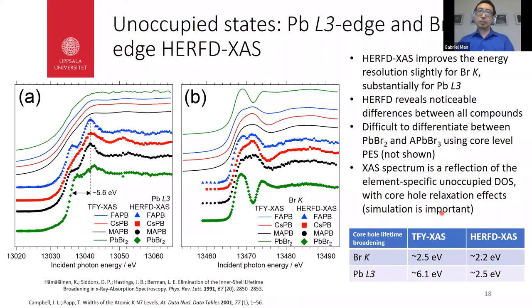To facilitate a more quantitative comparison, we can take the HERFD-XAS fine cut and compare all of the compounds together. In figure A, this is the lead L3 XAS spectra. There are two types of XAS spectra. The solid lines are for the conventional, total fluorescence yield X-ray absorption spectra, and the markers are for the HERFD-XAS spectra. We can notice immediately that the TFY spectra basically look like a Gaussian broadened step function. That's because the core lifetime broadening for lead L3 is rather large, and there's not a lot we can do about it. But because we have a spectrometer, we can trade the 6.1 eV for 2.5 eV.